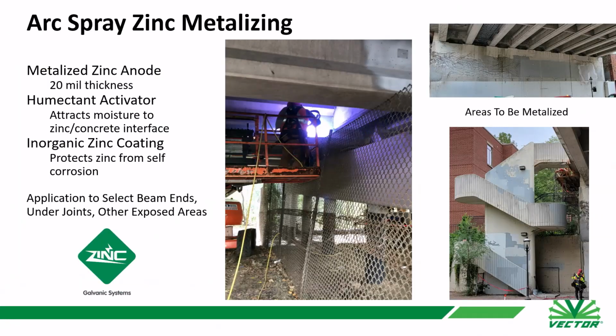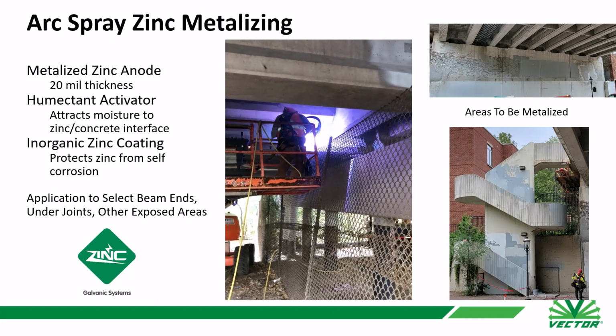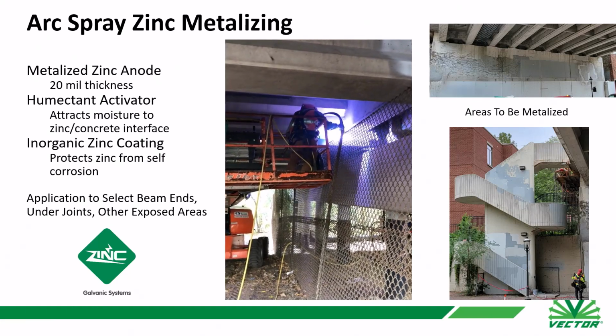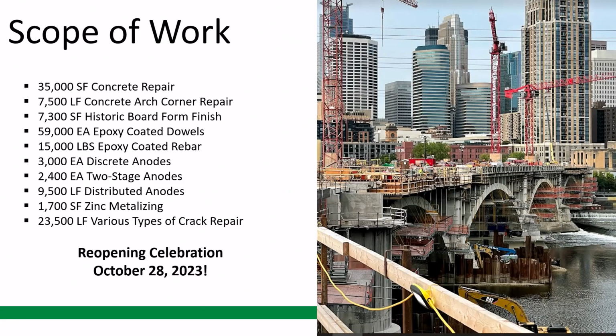And then in some areas, particularly around the abutments and some of these staircases they had, they basically use a metallized zinc anode on the surface, which is a whole other kind of surface applied distributed galvanic protection system. And there's the metallizing taking place there. So it's really nice, a real combination of solutions, a lot of concrete repair, a lot of galvanic protection, et cetera. And I'm sure we have some people in Minnesota supposed to have the opening celebration here at the end of the month. So big investment to extend the life of an old historic structure.